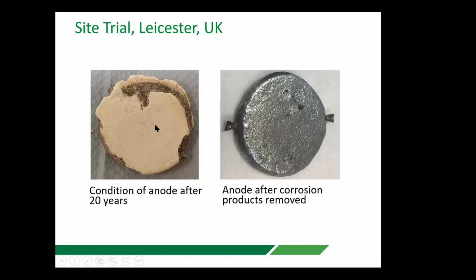Looking at another anode, this one from the patch after 20 years, we could see the corrosion product build up around where the actual initial zinc surface was. But removing that, you could see that there was still quite a large zinc core that was available for further corrosion and further protection of the steel reinforcement. So this was after 20 years, and we were able to work out the efficiency, i.e. the amount of zinc that was consumed theoretically by using Faraday's law compared to the mass loss of that particular anode, and we found that the efficiency was roughly, or at least, 70%. So 70% of the zinc was used to produce the current that was delivered to the steel. 30% is lost due to self-corrosion.